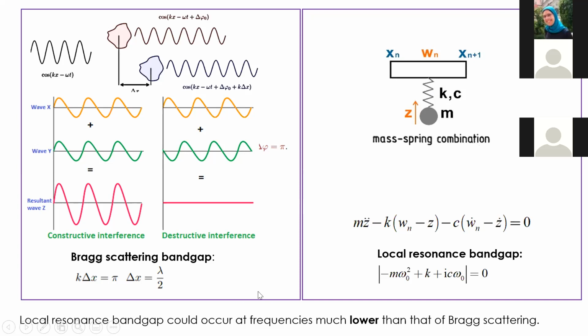As I have just explained, backscattering requires the distance between the two particles, that is the dimensions of the lattice, to be equal to half of the wavelength. At low frequencies, we know the wavelength is very large. So in order to achieve these backscattering band gaps, we would need very large structures. But as for the local resonance band gaps, since they are caused by the resonance of the oscillators, they can occur at very low frequencies. That's why for low frequency vibration attenuation, we usually adopt local resonance band gaps.